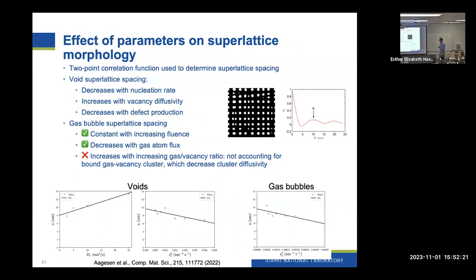We looked a little bit then at some of the effects of these parameter choices on the superlattice morphology. So we characterized this with a two-point correlation function approach. We developed some relationships between the superlattice spacing and the model parameters and the observed microstructures. And so in most cases, we were consistent with the experimental observations.